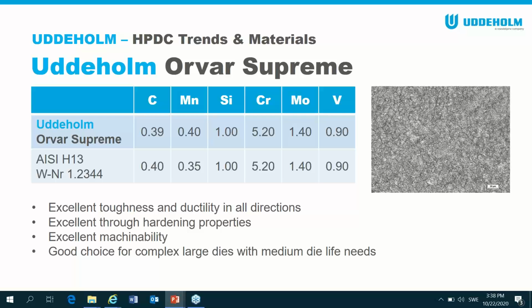Orvar Supreme, or what can I say about Orvar? It's a very, very consistent, high quality H13. And I would argue it's the best in the world as a stock standard off the shelf. Very consistent. And don't forget, this material benefits from all the process improvements we've made here in general investments, heat treatment, and so on. So if you look at your Charpy V values on your cert that you get for Orvar Supreme, you're most likely going to see figures well over 20 joules. Very, very good material. And the cleanliness is excellent as well.